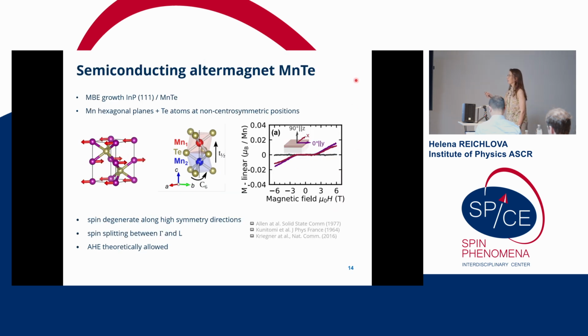So here, manganese telluride is one example of a semiconductor which is at the same time altermagnetic. And when I say semiconductor, it's a real semiconductor. It's not something basically metallic like some of these semiconductors which were ferromagnetic. It's a beautiful semiconductor which is well known to the community, so it can also be grown in very high quality by MBE on indium phosphide, and these hexagonal planes have tellurium cages around the manganese atoms. When we look at two manganese atoms with opposite spin, and we look at how the tellurium cages look around them, we see that it's not a simple translation, but a translation combined with a rotation. And this is exactly what fulfills our altermagnetic criteria.